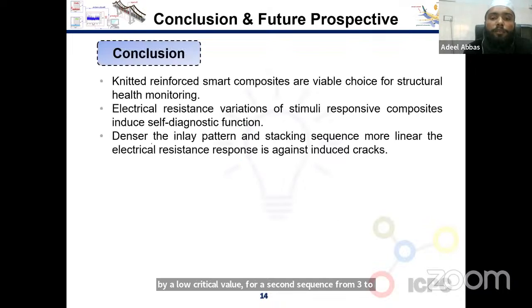From the results, we conclude that knitted reinforced smart composites are a viable choice for structural health monitoring, and these can sense the mechanical changes in composites with respect to their electrical resistance. By making our inlay pattern dense, for example, changing from 6 by 1 to 3 by 1 inlay pattern, and making the stacking sequence more dense, there is a linear increase in electrical resistance against mechanical damages.